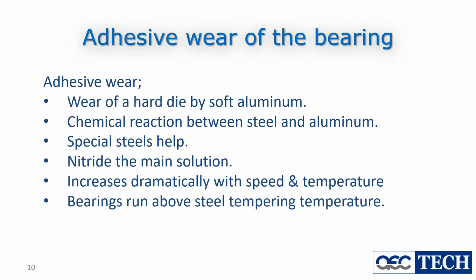So as I said, bearings are hot. They can reach 600 degrees C, which is the tempering temperature of the hot working tool steel, such as H13. And then it will temper the H13, so that when the H13 tempers, no matter what is at the surface, even if the nitride layer, if the H13 tempers to below 40 Rockwell C, the nitride layer will peel off, and then you'll touch the surface of the steel without the coating.